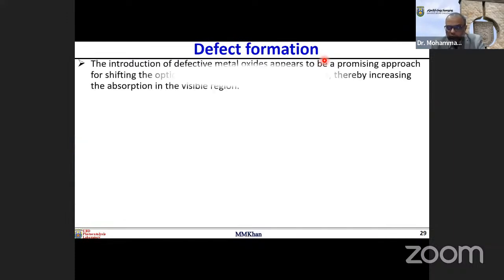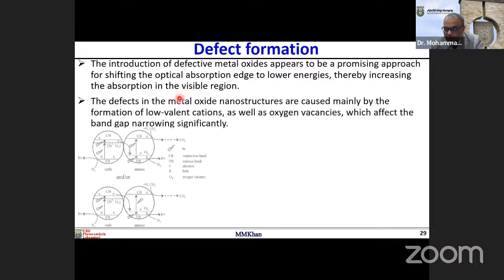And the next one is defect formation. Sometimes, as I told before, the pure materials are not very good, in the sense of the response that you are looking for. So what we do, we create some defects. The introduction of defective metal oxides appears to be a promising approach for shifting the optical absorption edge to lower energies, thereby increasing the absorption in the visible region.